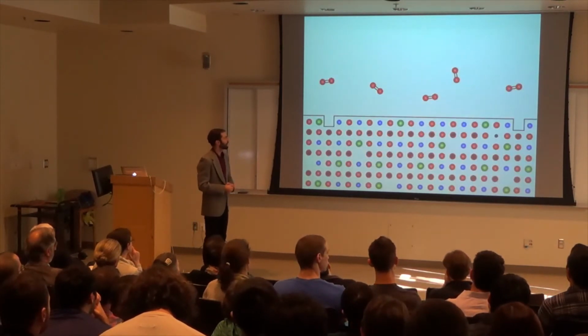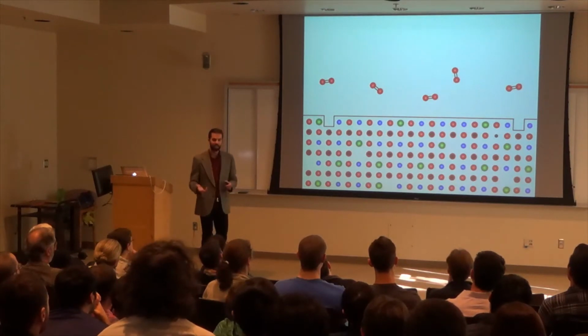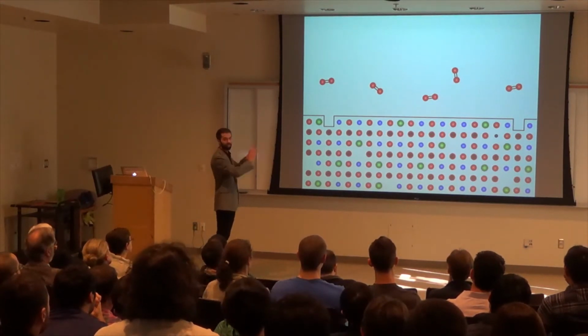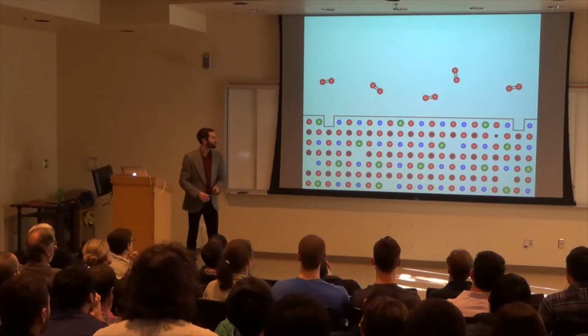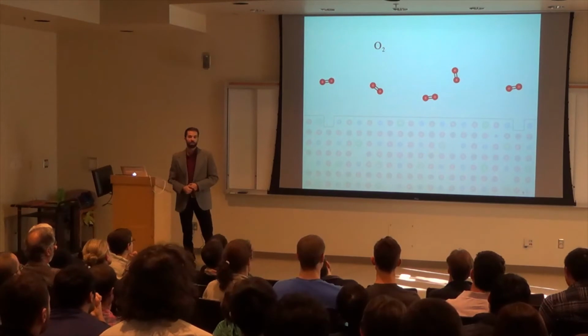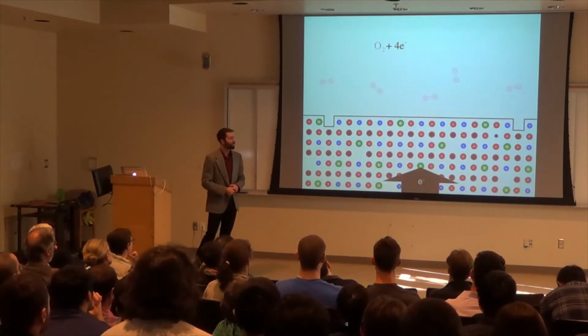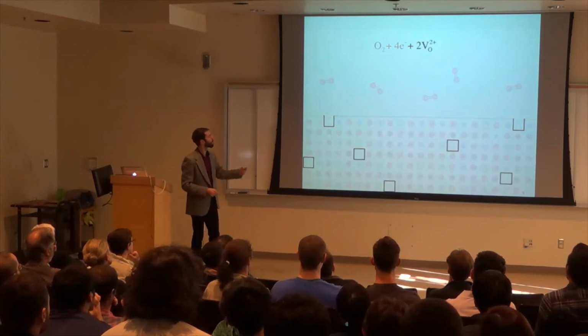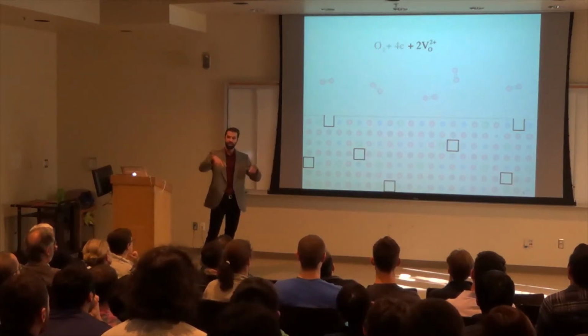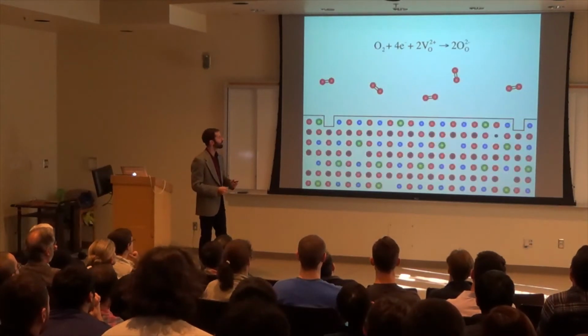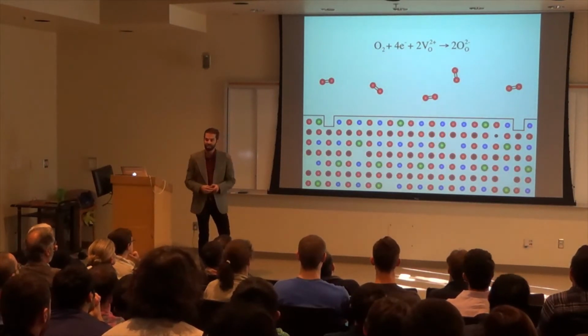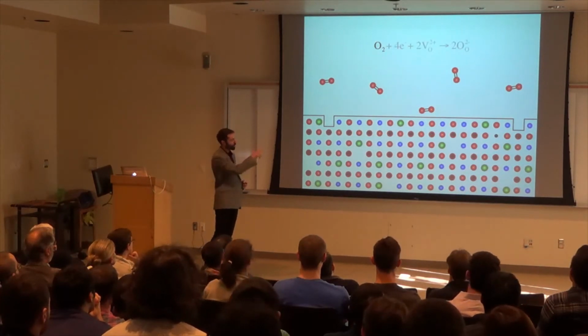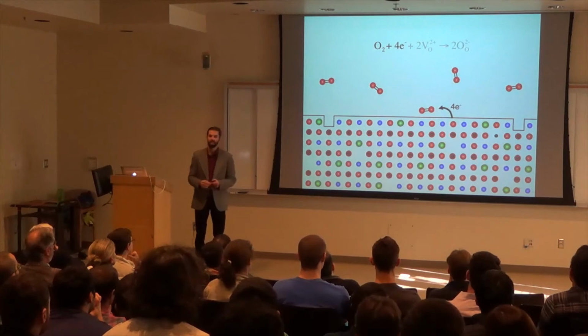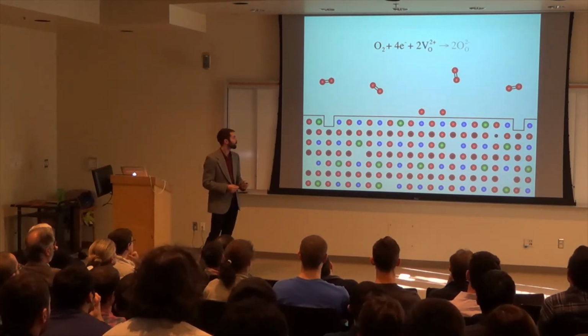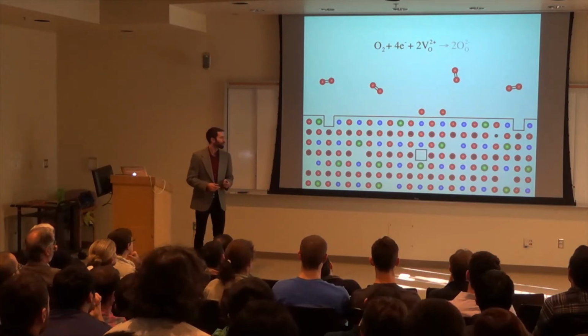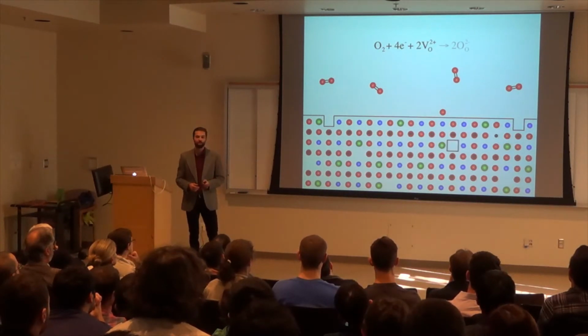So now let's zoom in to what the reaction looks like at the surface of the material. This is the side view of that unit cell as a single crystal. For the reaction to occur, we must have oxygen gas present. We must have electrons present, and these come from the local material. And then we also have oxygen vacancies, so the oxygen can jump into the material surface itself. And then finally, oxygen is now incorporated into the material. So this looks like oxygen adsorbs to the surface. The electrons must break the double bond of oxygen, and then it adsorbs onto the surface. And then oxygen vacancies must travel and be present so that the oxygen atoms can jump into the surface of the material there.